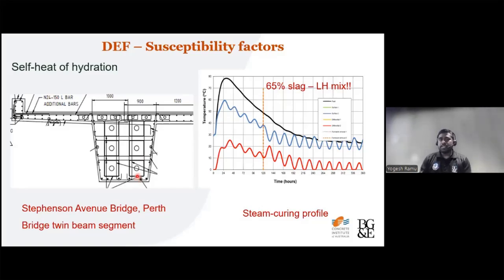It was planned with a 65 MPa concrete mix, which had 65% slag in it. Even with 65% slag, if it starts around 29 degrees Celsius, it can potentially reach up to 80 degrees Celsius. Sorry, this is not a steam curing profile. This is a prediction from CIRIA C766. So you can see not only precast concrete can go up to very high temperatures. Even in-situ concrete, even with 65% slag in it, can go up to roughly 80 degrees Celsius if it is not controlled properly at the early stage, if it is a very large concrete element.